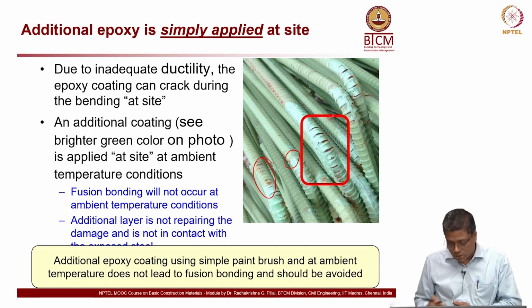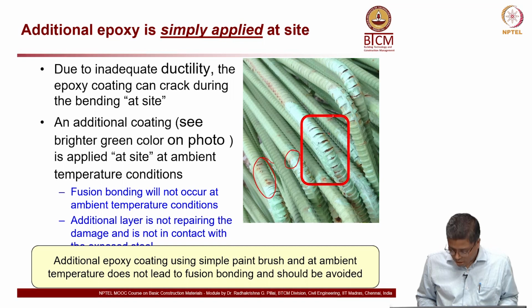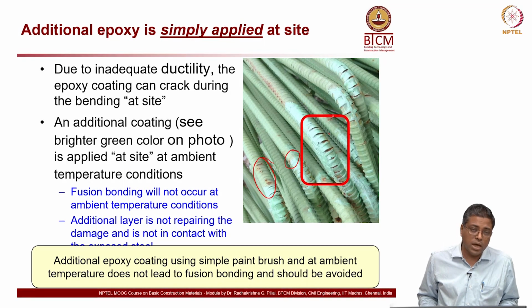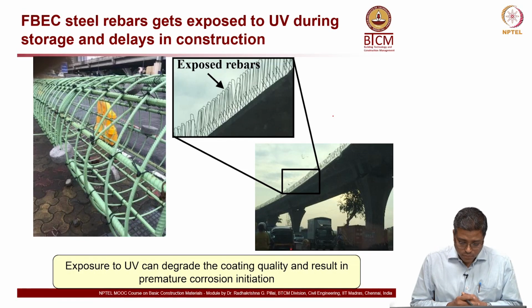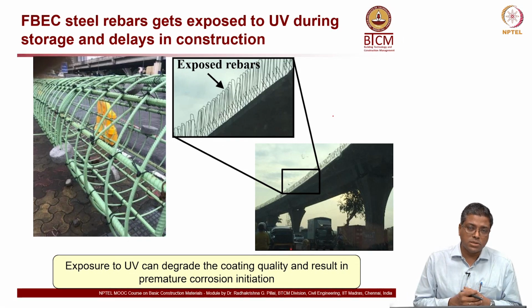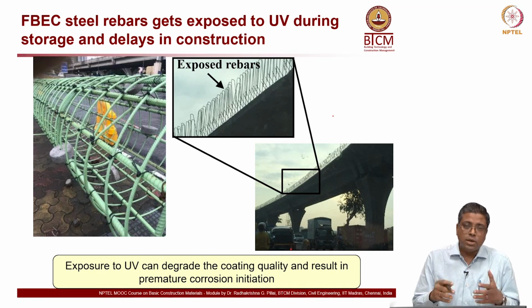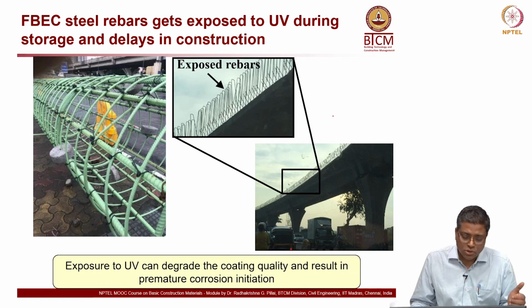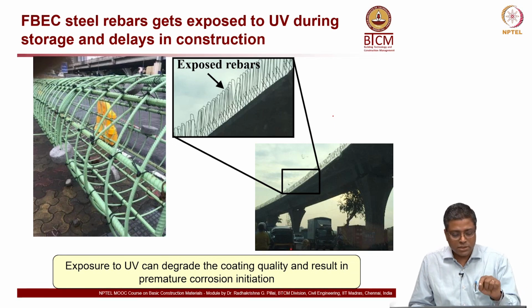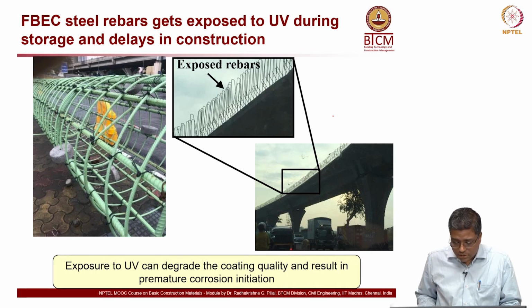So cracking of epoxy is not at all a good idea, whether it is due to mechanical damage or sunlight or whatever be the way, we should not allow this epoxy to crack. Here is another example, pictures from construction sites where these bars are exposed to sunlight for a long period of time, months or even weeks at least. So all these will get exposed to the sunlight, and sunlight has UV radiation, and that will make this epoxy crack. Okay, that will crack this epoxy coating, and these cracks are not something which you can really see with your naked eyes until it is severely corroded.